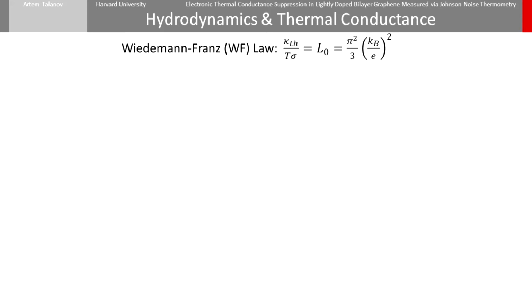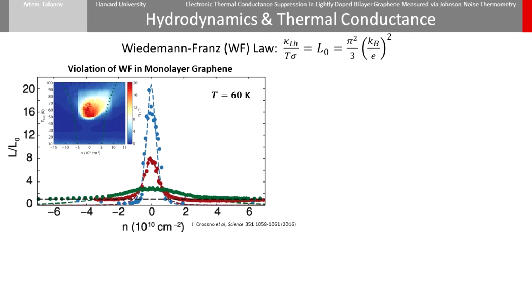In conventional non-hydrodynamic materials, the thermal conductivity kappa follows the Wiedemann-Franz law, where the ratio of the thermal conductivity to temperature and electrical conductivity is a constant called the Lorentz number, which is expressed in terms of fundamental constants. If an electron system is found to violate this law, it is a candidate for hydrodynamic transport. Previously in our group, we measured the thermal conductivity of clean monolayer graphene at the charge neutrality point at 60 Kelvin. We found a 20-fold enhancement relative to the Wiedemann-Franz law.